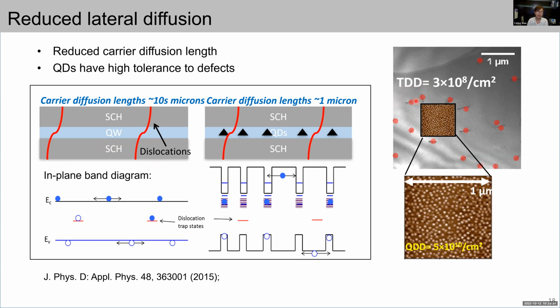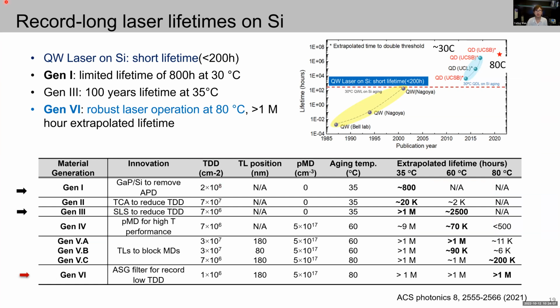For example, in this TEM image, the red points refer to the defects, and the yellow dots refer to the quantum dots. And you can see that even with a very high threading dislocation density, we are talking about 3e8 or so, because the dot density is still more than 2 orders of magnitude larger than the dislocation density, and because each dot is independent, one threading dislocation line in the active region can only kill one or a few dots, and the majority of the dots are not affected. So the device can still work efficiently. This much improved defect tolerance gives rise to record device lifetime on silicon.